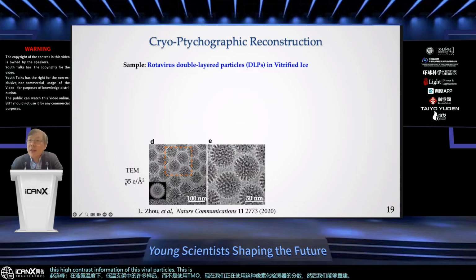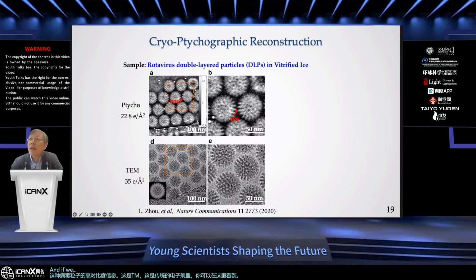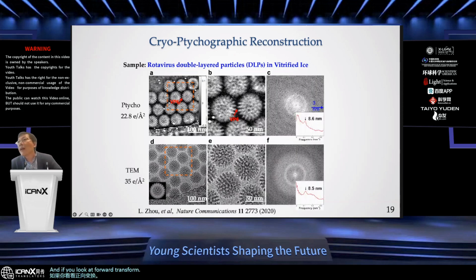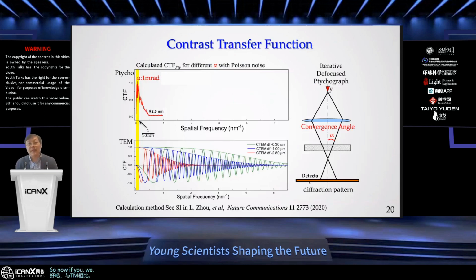This is TEM, with conventional electron dose, as you can see here. And if we change to ptychography phase imaging, now the contrast of the viral particles is very strong compared to conventional TEM. If you look at the Fourier transform of this image, the reason why we're able to see the strong contrast is the low frequency content within this Fourier transform, compared to the TEM mode. So now, if you want to understand why ptychography has better contrast, we need to look at the so-called contrast transfer function.